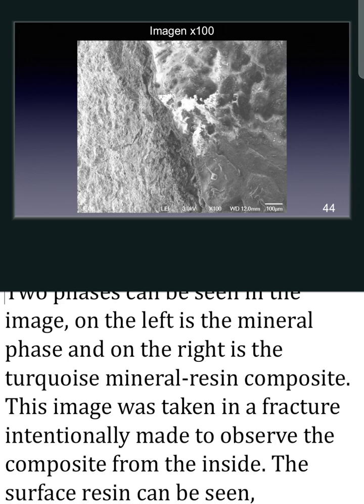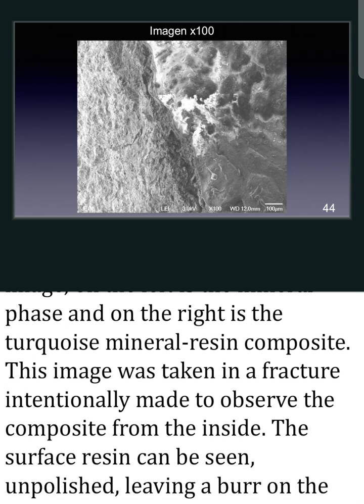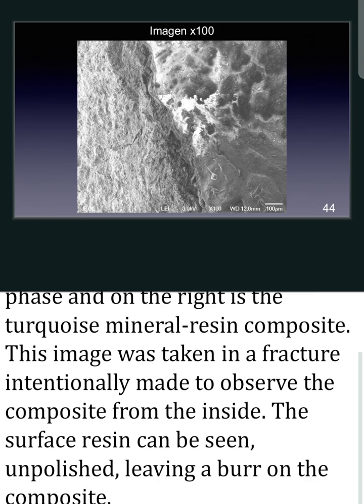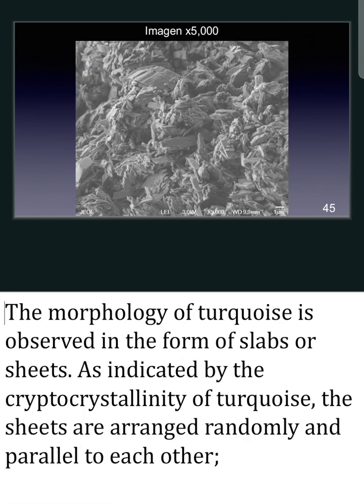This image was taken of a fracture intentionally made to observe the composite from the inside. The surface resin can be seen unpolished, leaving a burr on the composite. The morphology of turquoise is observed in the form of slabs or sheets. As indicated by the cryptocrystallinity of turquoise, the sheets are arranged randomly and parallel to each other.